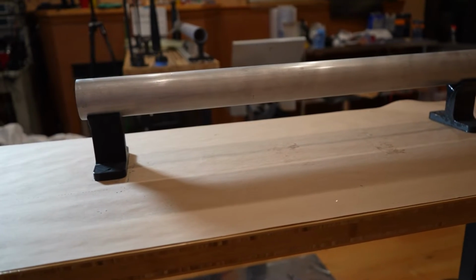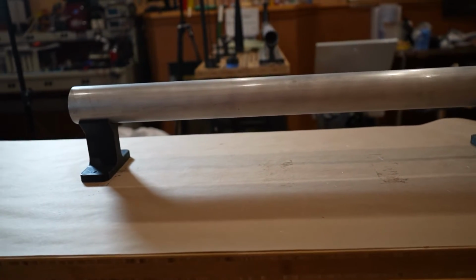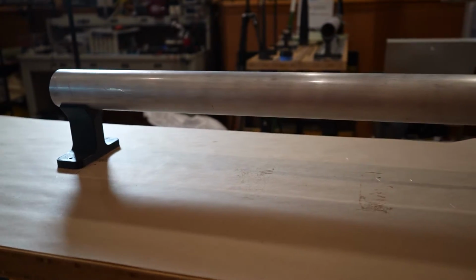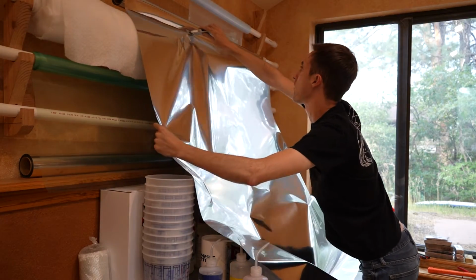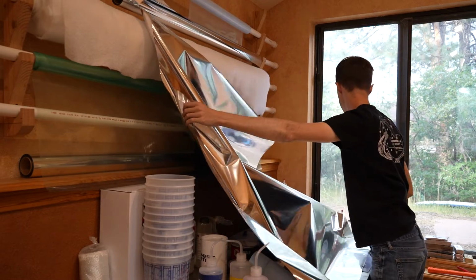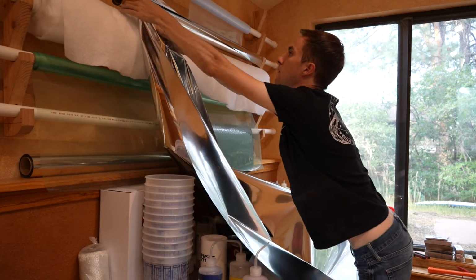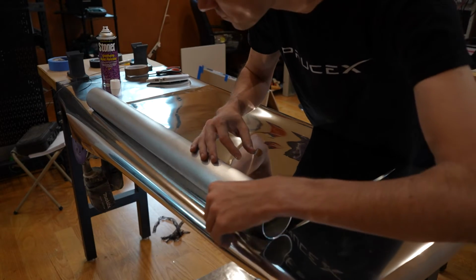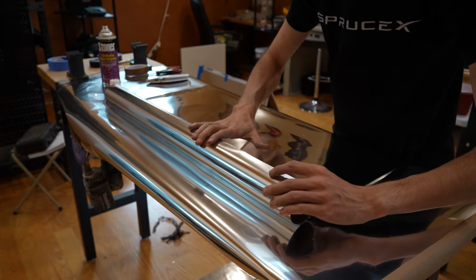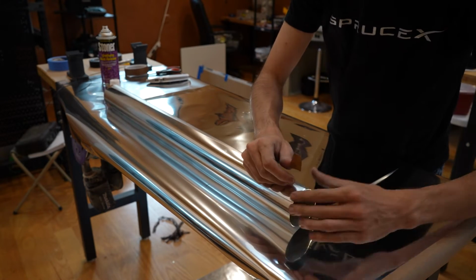This project starts with an aluminum mandrel. I use an aluminum tube, which is sanded to 800 grit and then polished. I wrap this mandrel tight with a layer of mylar film. This is taped onto the mandrel so I can get a tight wrap, but just at the edges so I can remove it later. This type of tape is called Teflon tape, and it's coated in PTFE, so the epoxy doesn't stick to it.